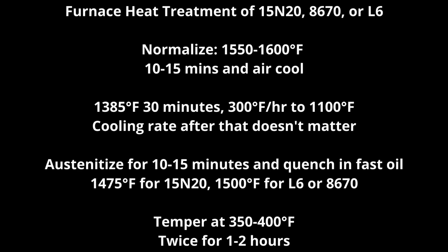Then temper twice, 1 to 2 hours each. You got to air cool in between. And then temper between 350 and 400. Higher than 400, you are in danger of getting tempered martensite embrittlement. Lower than 350, and you are in danger of insufficient tempering, as we saw with 15N20, where the 300-degree temper was much lower in toughness.